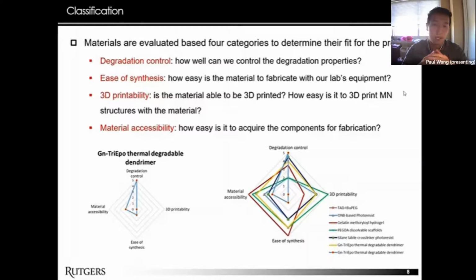We can't really quantify aspects like 3D printability or ease of synthesis with units. However, since we're just interested in selecting material, this rating system is sufficient enough. The figure at the bottom left is an example of one of the materials examined called Gn-TriEpo. It's a thermal degradable polymer, and as you can see with the chart, it has a 0 in 3D printability, which means it can't be 3D printed. Its other scores are also pretty low, but it's very easy to customize the degradation behavior.